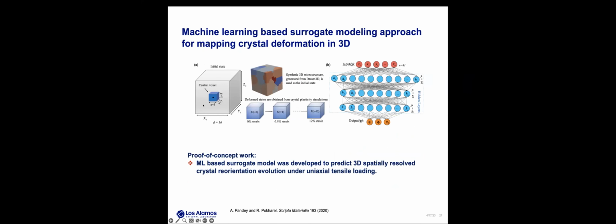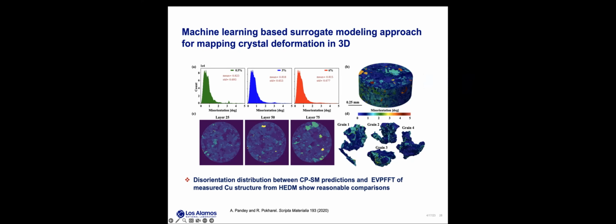So one thing to note is, in this case, this was one of the first times us developing these tools. So we manually generated local 3D regions to feed into our model, instead of using a CNN, which actually takes into account the spatial interactions. So anyway, the simulation-trained network was then used for predicting the experimentally measured microstructure data.